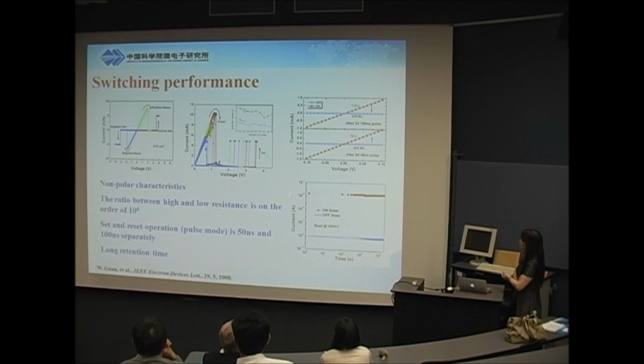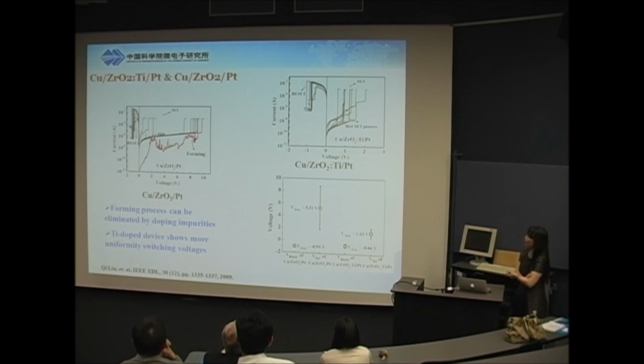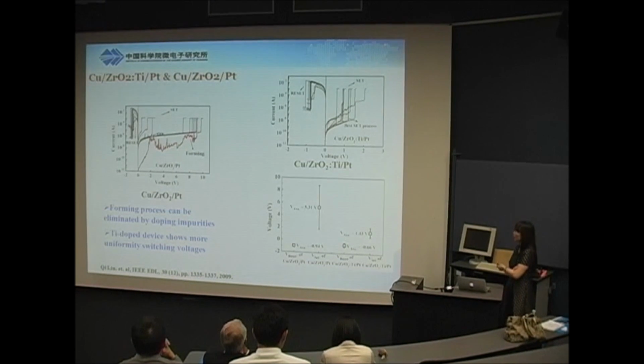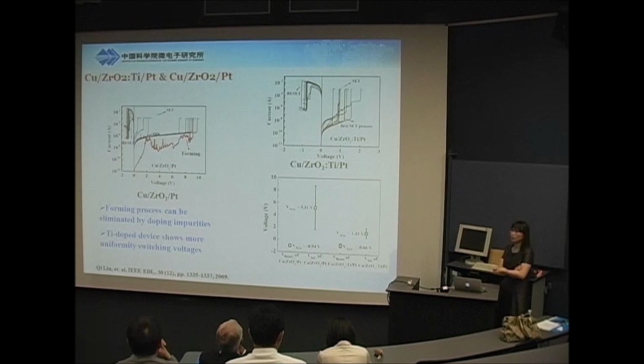So this device is doped with copper. Then we use titanium as a dopant. We can compare the undoped device with the doped device. After doping, both the set and reset parameters are narrowed a lot, which means the performance is greatly improved. Also, we can see that using a different dopant can also change the properties of this kind of device.